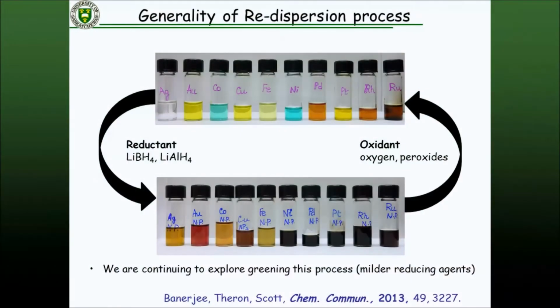One of the problems you have in this system is that lithium borohydride and lithium aluminum hydride are a little bit stronger reducing agents than one would like to use in these processes. This is the effect of using halide media. Metals oxidize much more easily in halide media, and you need much stronger reducing agents to re-reduce those metals in that same media. So this is one of the problems, that you can't actually use things like hydrogen gas, which is what we wanted to, very easily in these ionic liquids. Most of these metals actually won't reduce under hydrogen gas in these halide media. They certainly will in water, but in these particular solvents, they will not.